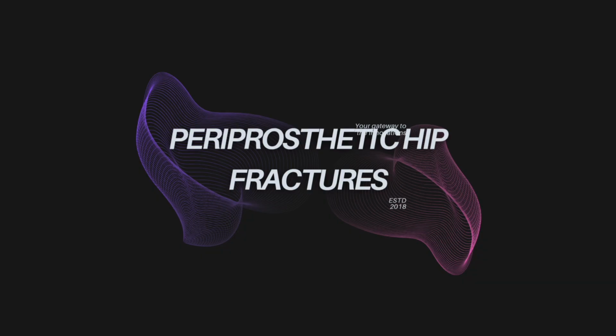Let's break those down. Sure. Stress shielding happens when the rigid metal takes all the mechanical load, causing the bone underneath it to weaken and resorb because it's no longer being stimulated by weight. Cortical notching is when that rigid metal wire physically digs a groove into the hard outer layer of the bone.